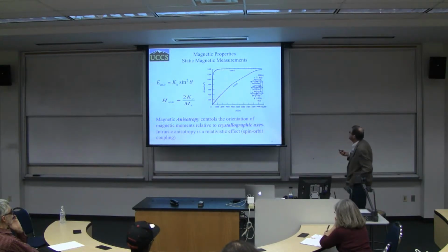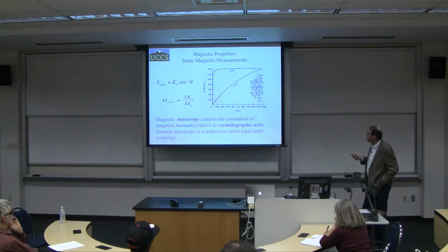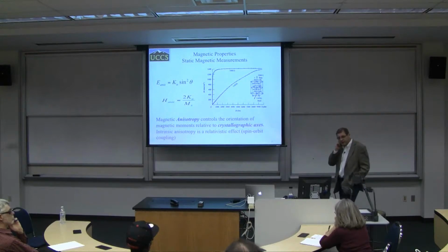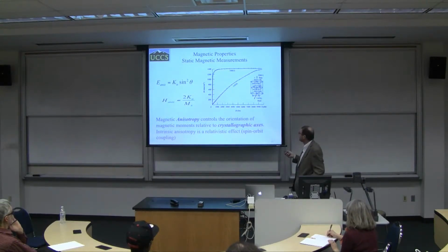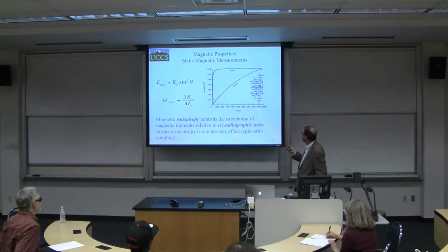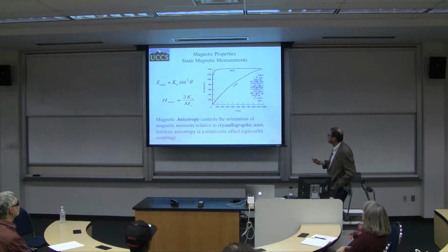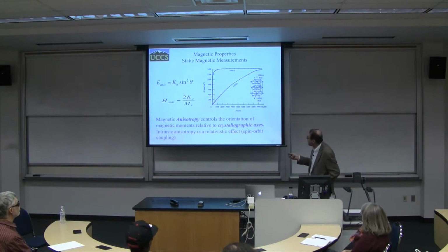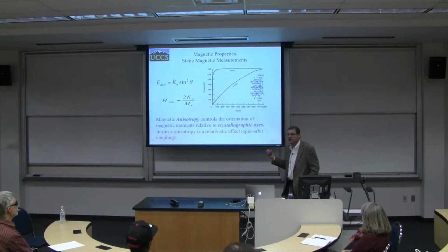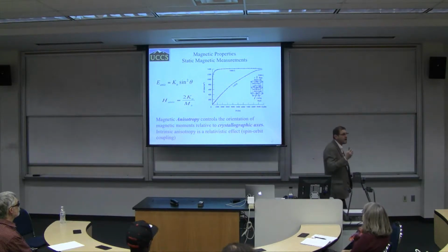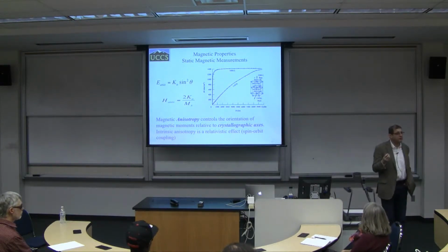What is important is that I have these differences, and therefore I must have some anisotropy energy associated with my magnetic system. This anisotropy energy is typically measured with respect to a certain direction, in this case the c-axis, and a certain constant. Every time you have an energy of a magnetic system, you have an effective field associated with it.